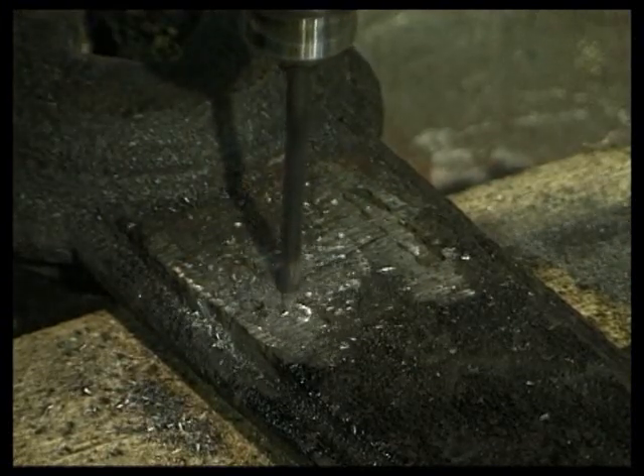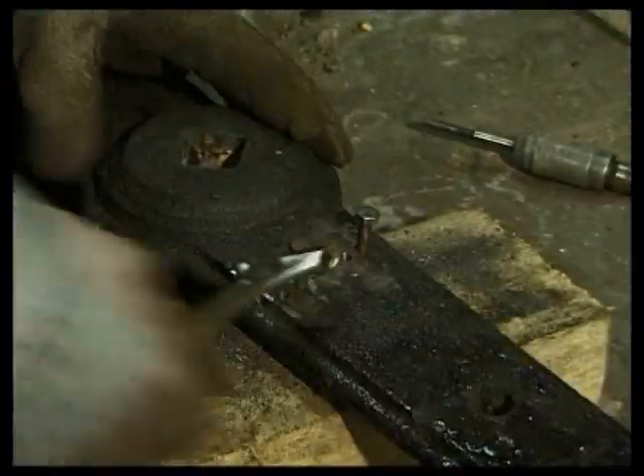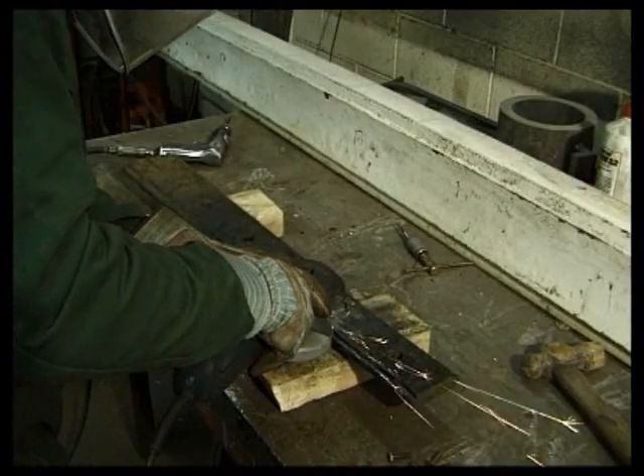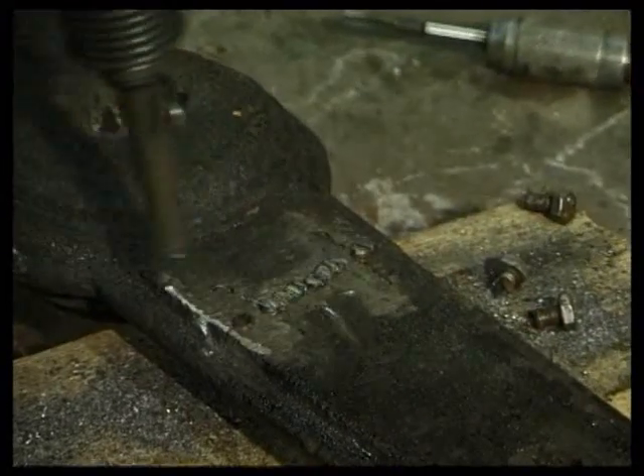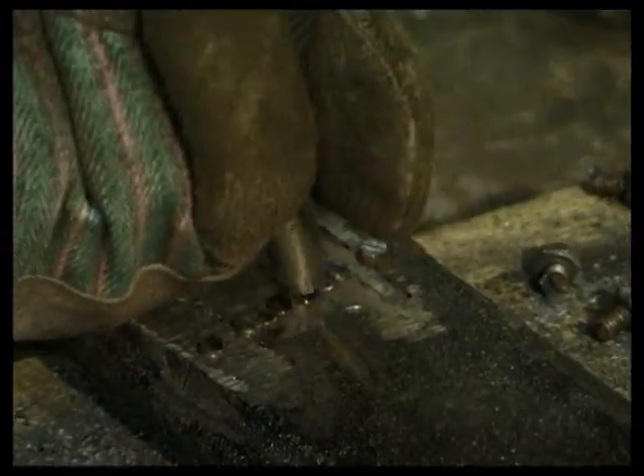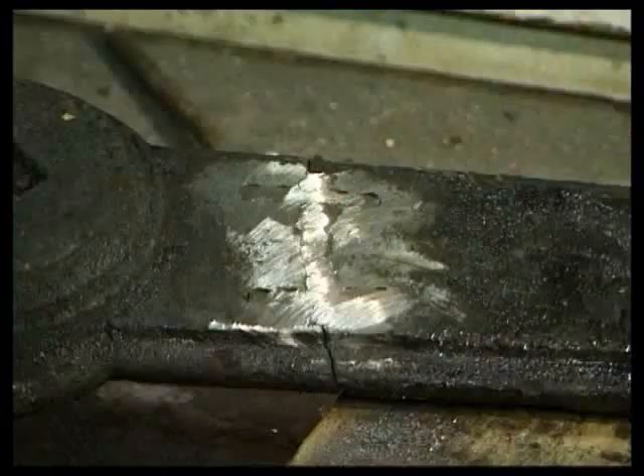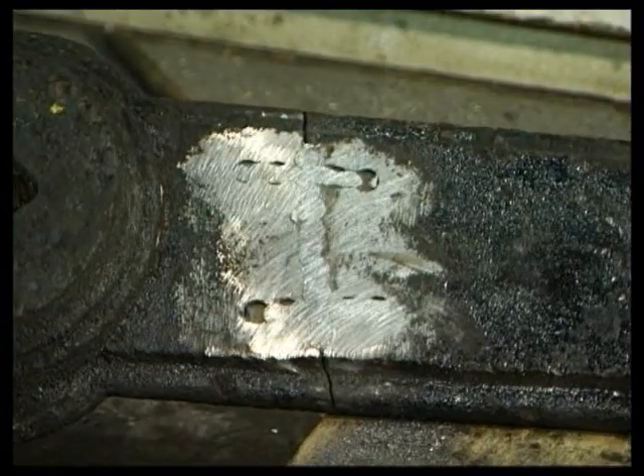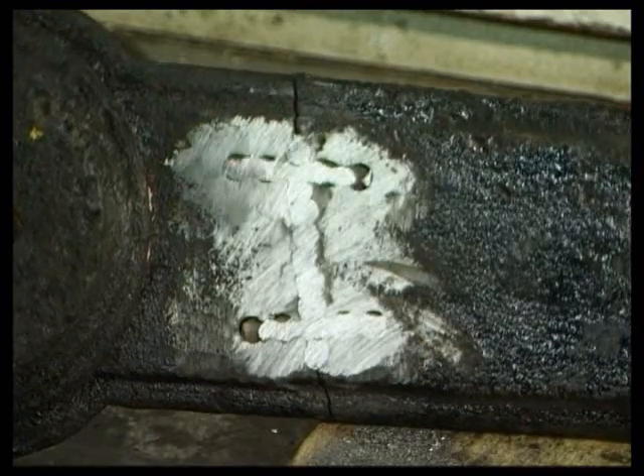Holes are then drilled along the crack and overlapping bolts screwed in to provide a seal and prevent the broken sections sliding out of alignment. Finally, the protruding parts of the bolts are cut off and all is dressed tight. The result is a permanent watertight repair without the use of heat or sealants that can be carried out on site with portable pneumatic equipment.